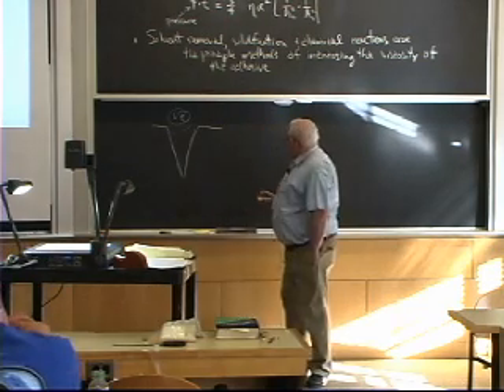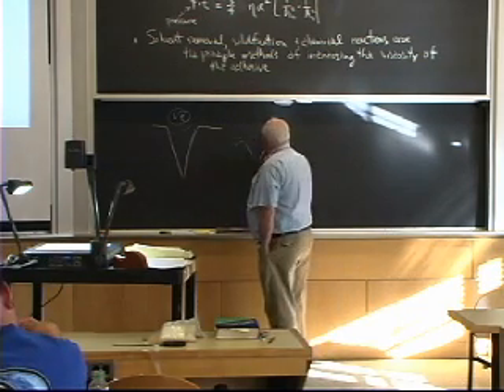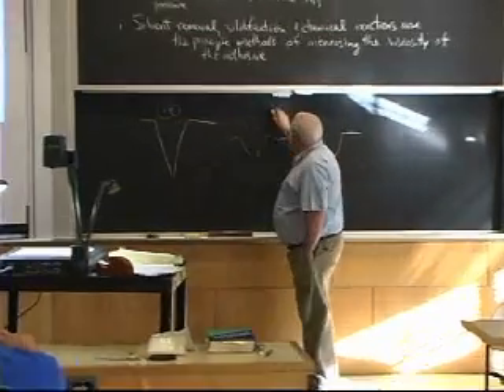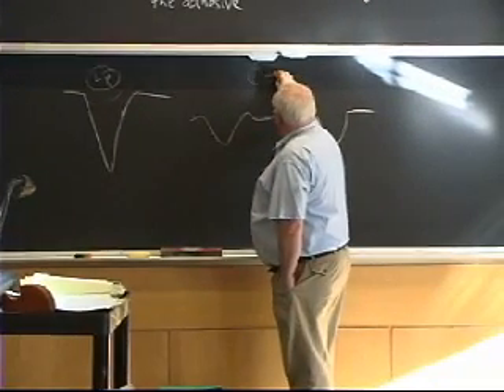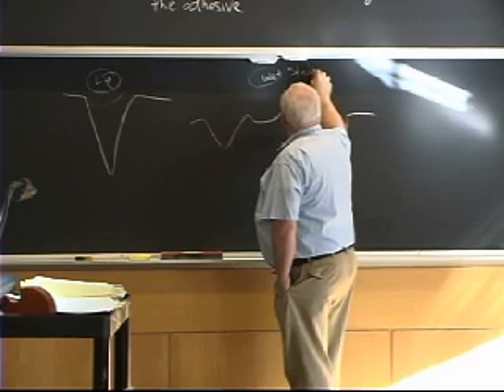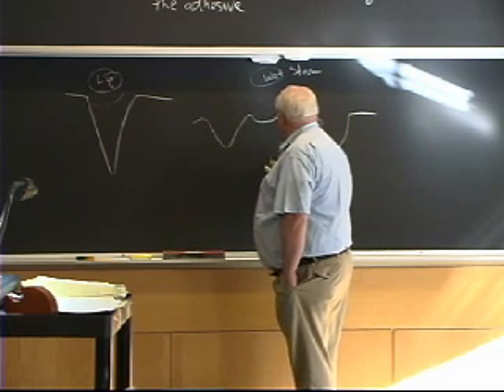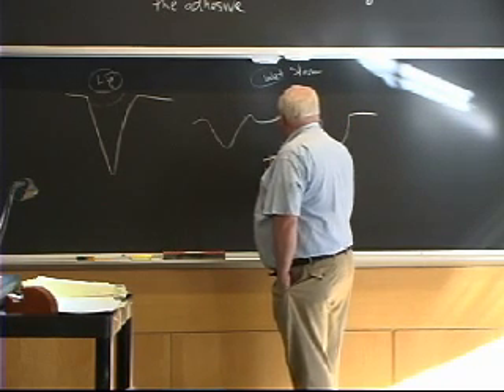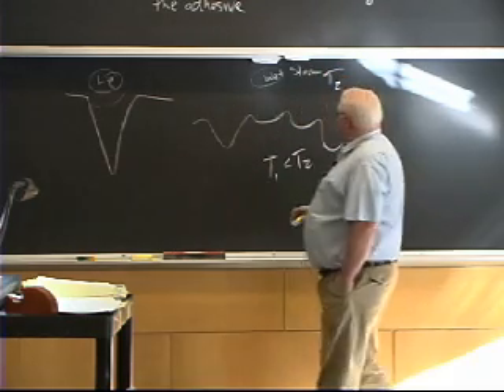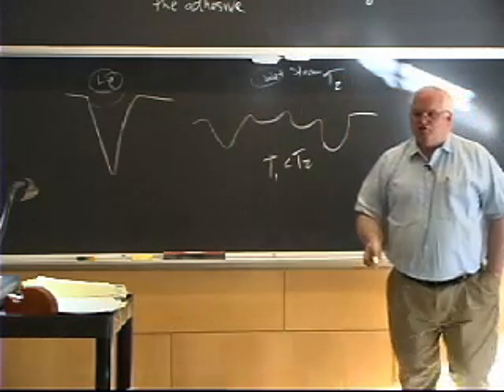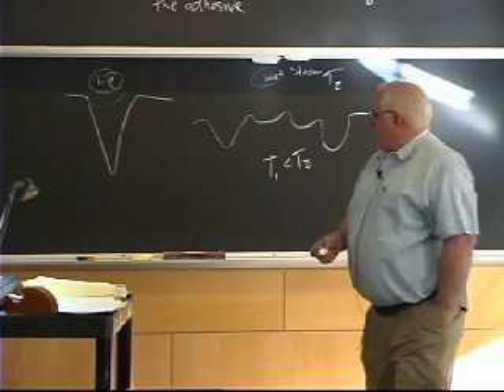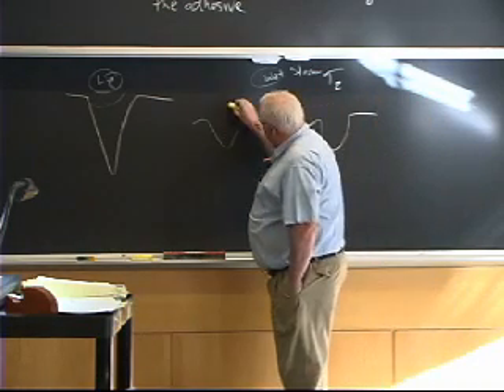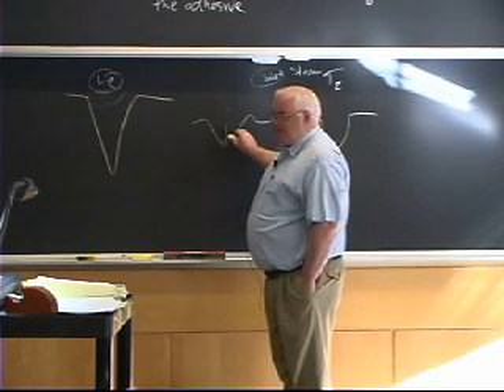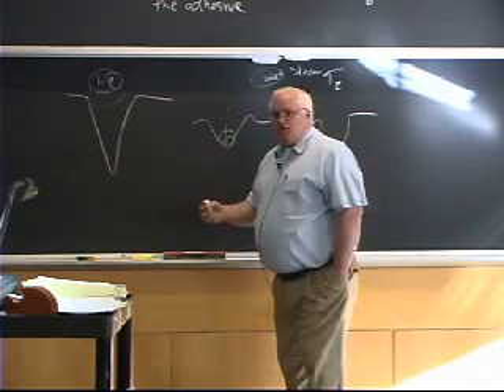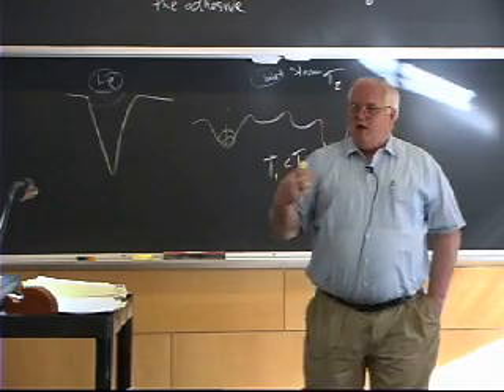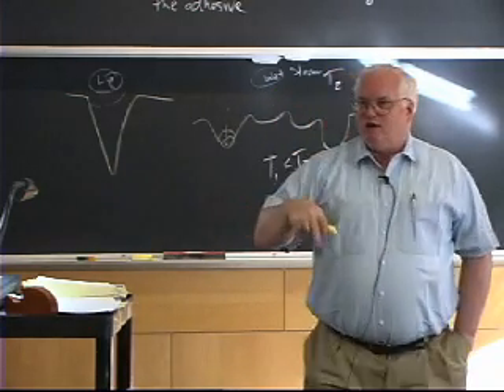Supposedly, if you take Teflon with its rough surface like this and you expose it to wet steam or condensing steam, so if your steam is up here at some temperature T2 and you have your Teflon chilled a little bit, you'll condense the steam. The gas molecules can get down here, and if they condense down here, they're going to nucleate and grow from the bottom, and surface tension is going to keep the water that condenses down in there.